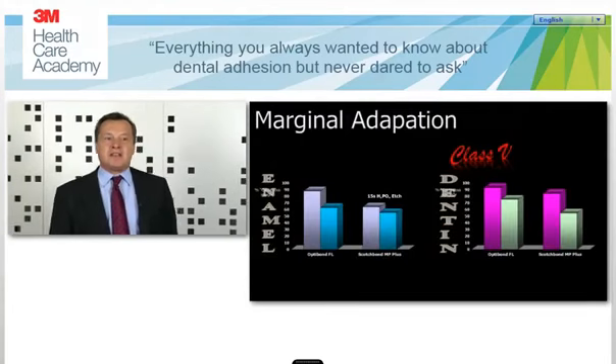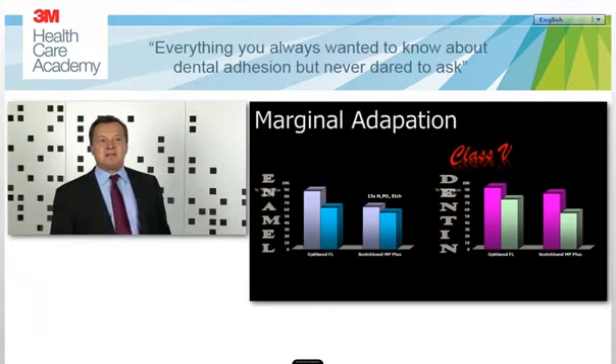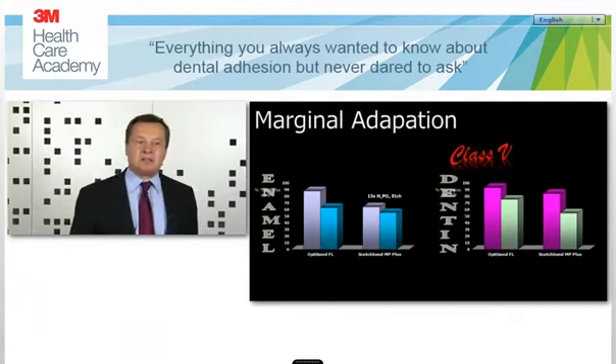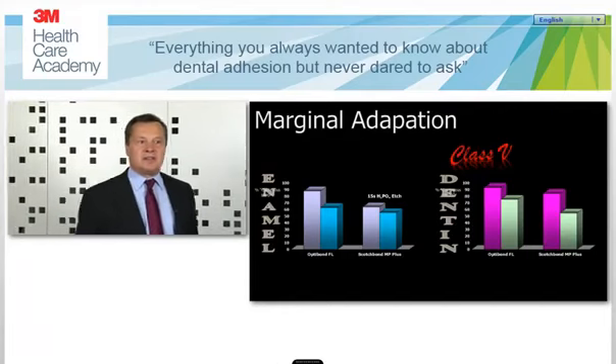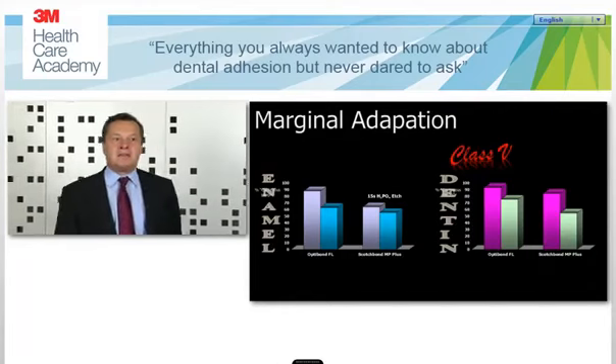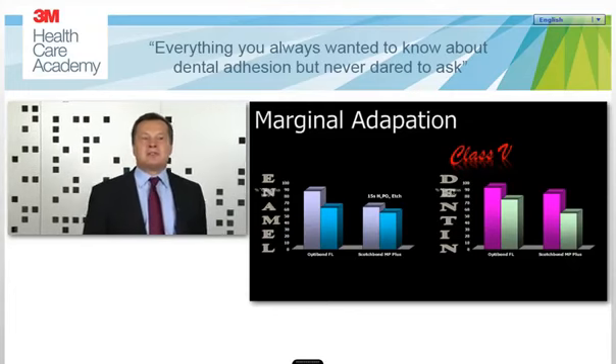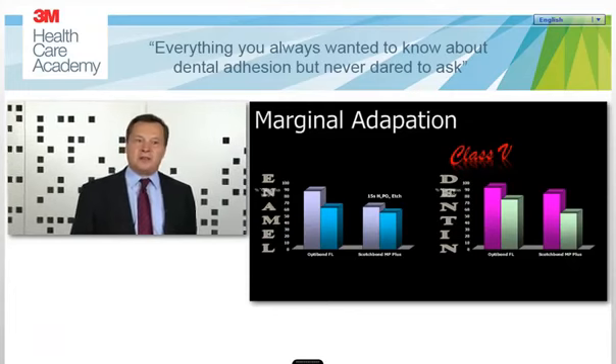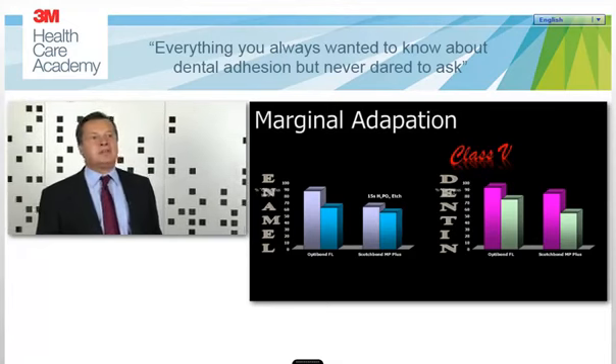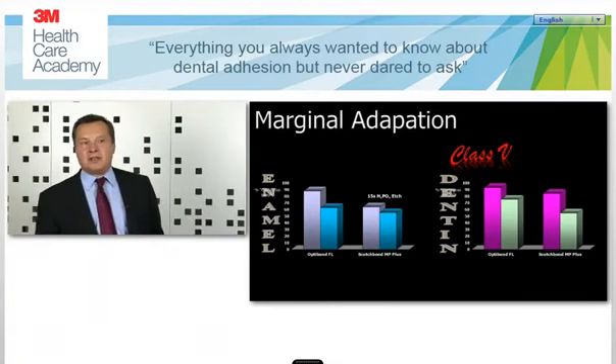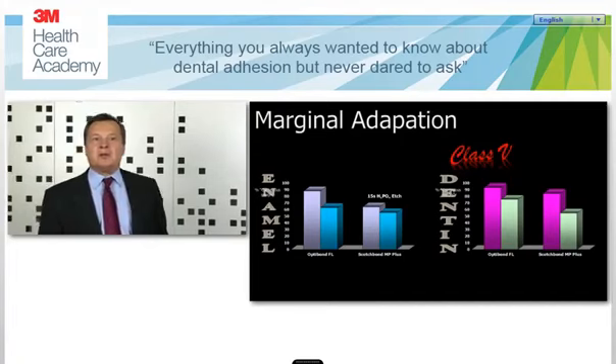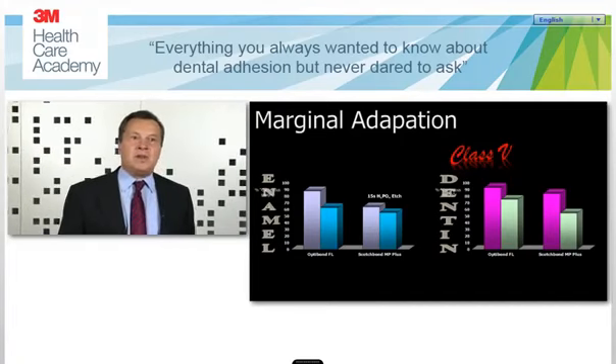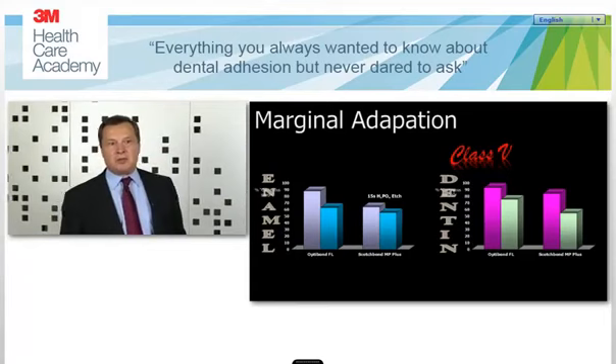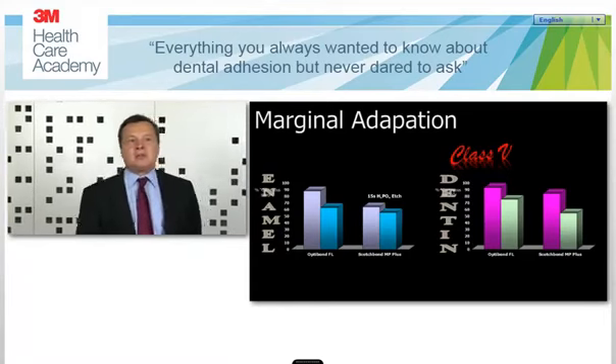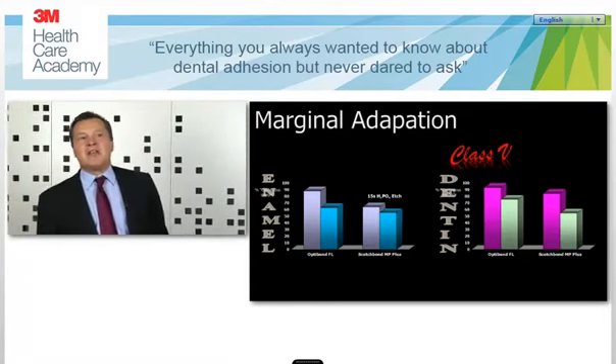Now, by checking on the marginal adaptation in enamel and in dentin, enamel on the left and dentin on the right, with our evaluation system, you will get the following results. On enamel, we have marginal adaptation of about 90% of continuous margins before loading in our chewing simulator and of around 70% after loading in our chewing simulator. When looking at dentin margins, we end up with about 90% of continuous margins before loading and at about 75% of continuous margins after loading.